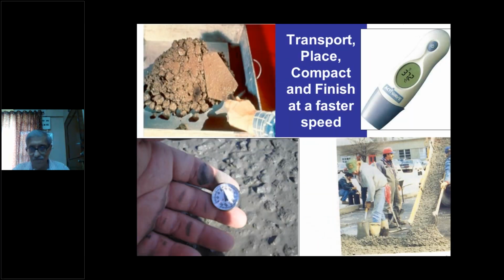Now you see a few photographs. I would like to show you this slide where a transit mixer is lowering the concrete through its chute. In hot weather, one has to be careful. The minimum slump which can be unloaded by a transit mixer without the input of manpower is about 50 millimeter. And if it goes less than that, then you need people to drag the mix from the chute. So this is one of my own observations when we did concreting at various places in the Bombay Thermal Power Project using transit mixers.